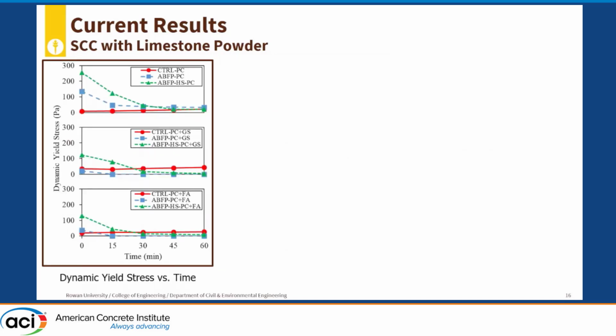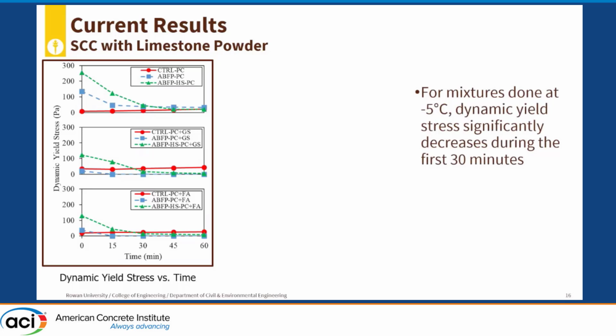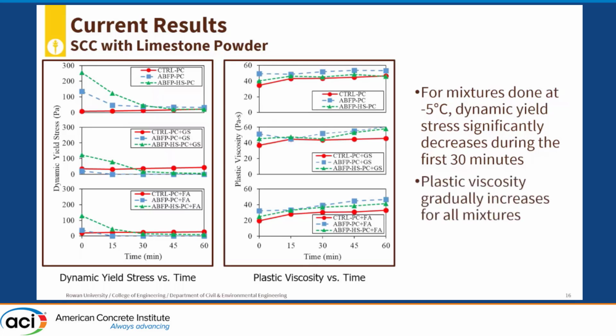We also measured the rheological properties. Here is the dynamic yield stress versus time. For control mixtures, the red ones, they have consistent dynamic yield stress over the first hour right after the mixing process. ABFP mixtures have a significantly higher dynamic yield stress right after mixing, which decreases after 15 minutes and then stays consistent until the 60-minute mark. Mixtures with hydration stabilizer have higher dynamic yield stress right after mixing, which goes down for 30 minutes and then stays consistent from 30 to 60 minutes, which is quite comparable to how the slump flow behaves. When dynamic yield stress decreases, slump flow increases. Plastic viscosity gradually increases with time for all mixtures.